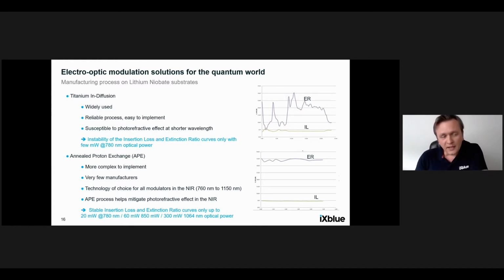So we actually use the annealed proton exchange technique to make the waveguide for near-infrared modulators. It's a bit more complex to implement, but it clearly provides an advantage in stability. If you look at that same graph, using a light at 780 nanometers, you have stability of the extinction ratio, and you have stability of the insertion loss. So today, we guarantee stable operation at 780 with 20 milliwatts, and at 850 with 60 milliwatts, which are pretty good values for waveguide-based electro-optic modulators.